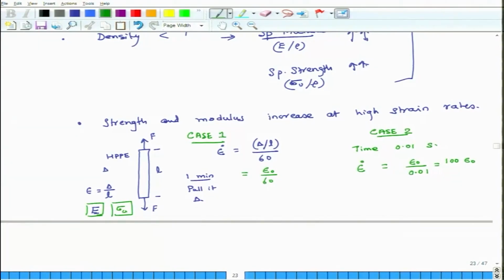And in this experiment, if I measure the Young's modulus, I will find that the Young's modulus in this case is extremely high, and also its strength. If I apply strains very fast, this HPPE material does not break at the same value as when the strain rate was low. Okay. So, its modulus and its strength increase very significantly at high strain rates. At low strain rates it will have some value, at high strain rates it increases very significantly.